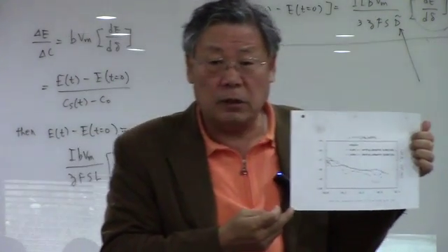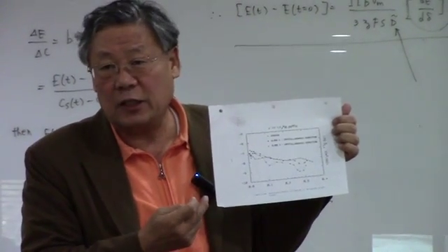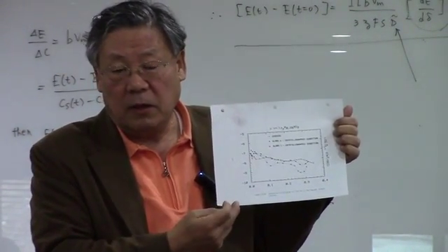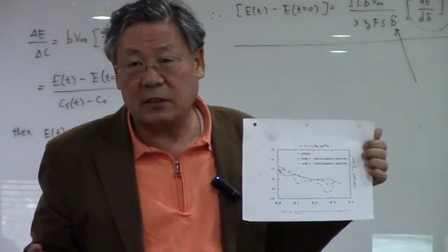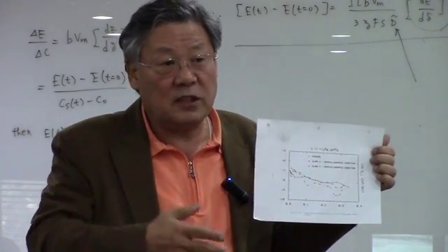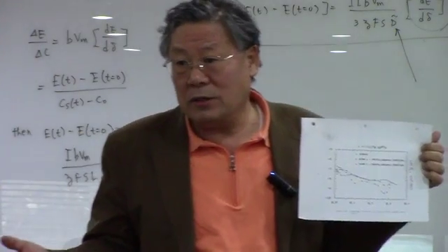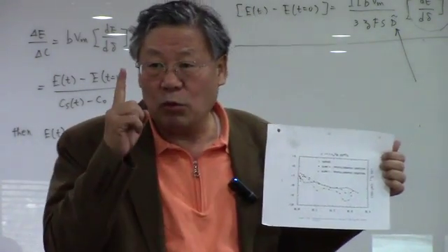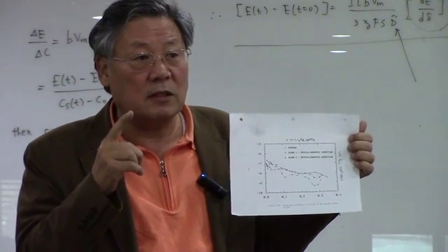Well, this is one of the examples of how powerful the electrochemical technique is to determine the diffusion coefficient. If you use the conventional or classical methodologies to determine the diffusion coefficient at one fixed value of your sample, it'll take many hours just to determine one point of a diffusion coefficient at some specific concentration of lithium.